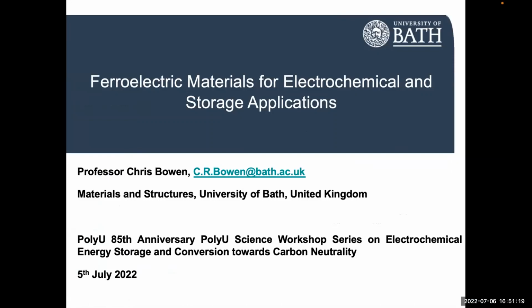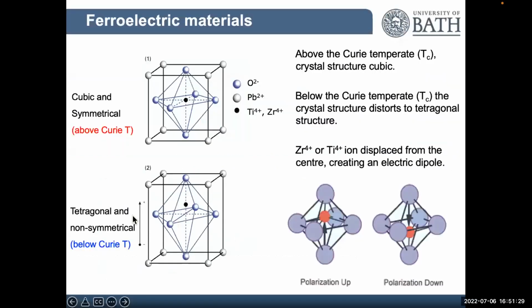So I'm going to talk about ferroelectric materials for electrochemical and storage applications. I'll make sure I'm finishing on time, at 10:30. At Bath we work on ferroelectric materials, and Haito has provided a really nice introduction. We tend to work on the ceramic materials. At high temperatures, these materials are ionically bonded, and at temperatures higher than the Curie temperature, they tend to be cubic, so they're symmetrical. There's no dipole and no piezo or ferroelectric properties. But below the Curie temperature, so at room temperature for many of the conventional ferroelectrics, we get a phase change and it's tetragonal. So we get a distortion.